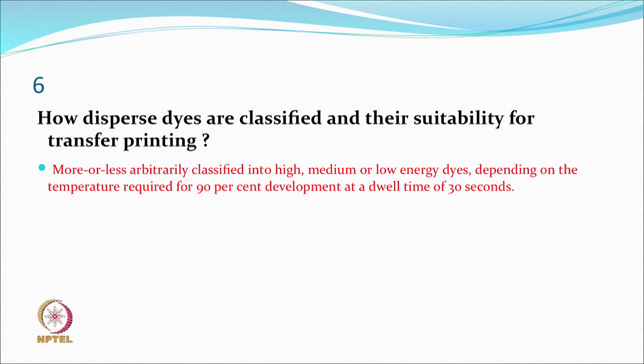If 90% transfer goes in 30 seconds, you are quite efficient. Otherwise, at higher temperatures, every dye keeps on vaporizing and diffusing. For polyester and nylon, you would not like to keep such material at very high temperatures for very long periods due to oxidative environments. You may still optimize at 45 seconds if you want more than 95% transfer.